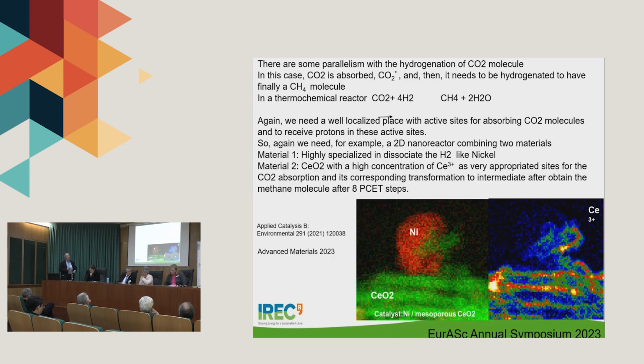And the other is a thermochemical example. For example, this is a mesoporous ceria, and this is a nanoparticle of nickel. What do you need to transform CO2 into methane? I can capture CO2, and then I can make synthesis of methane. I need hydrogen. And then, observe, I need 2 materials. Material 1, just to dissociate the hydrogen.